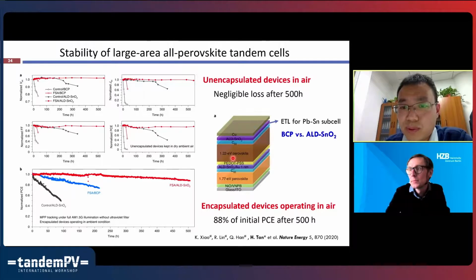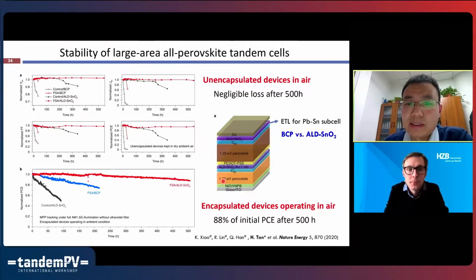I think at a low temperature, maybe the layer of fullerene, the carbon 60, is quite a good protection, because the water injection in this process is quite a small amount. And it's also very critical to control the amount of water you get inside the chamber. So this is also a very critical parameter when we do the processing. Usually if we make the tin oxide layer on top of the lead-based perovskite, this parameter is not so critical.